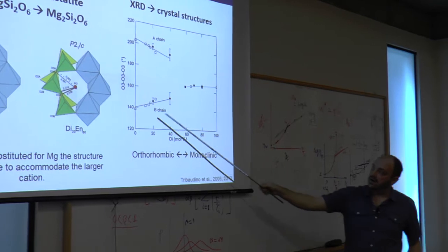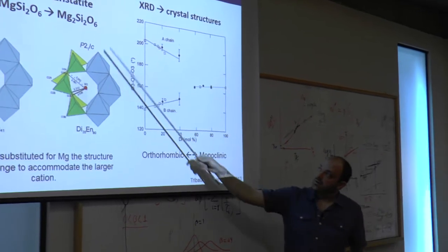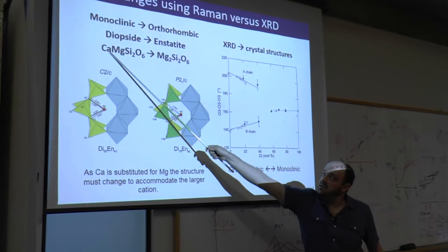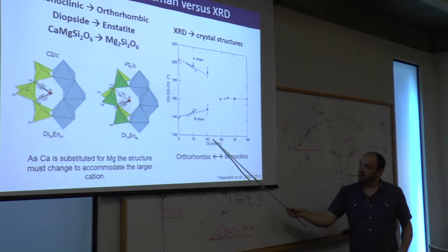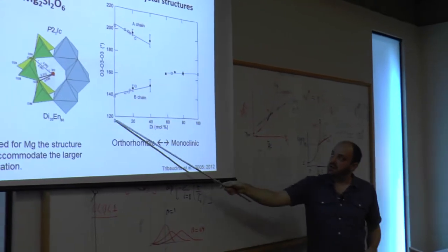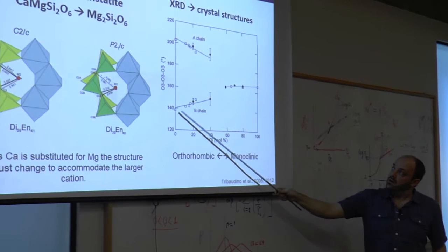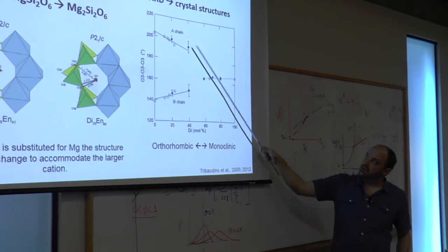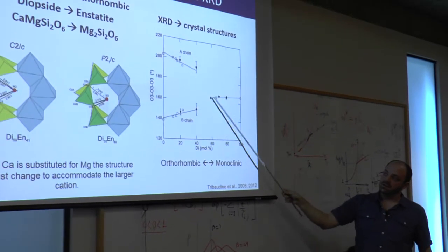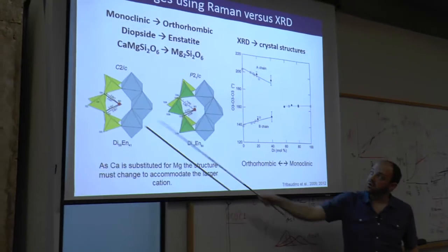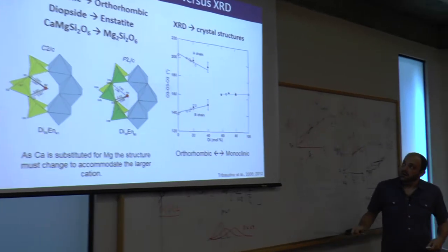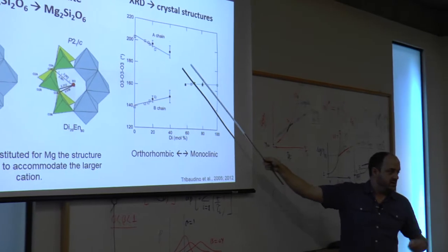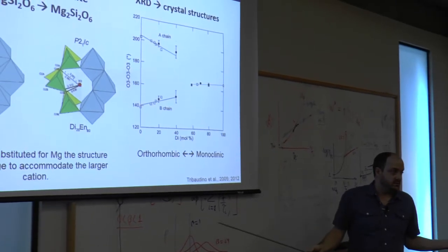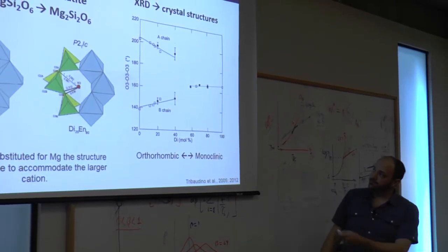And they show that when you have two chains, as you go from magnesium to adding calcium, going from the magnesium-rich member to the calcium-rich member, you have at some point a breakdown in the two chains where they collapse and become the same, as seen in the monoclinic structure here. So with XRD, we see a dramatic change with the phase change.